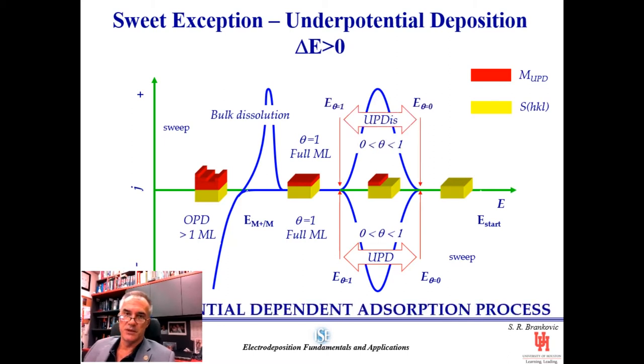The message to take home is that the UPD phenomenon is potential-dependent adsorption, and it's quite important to appreciate that by deciding which potential we hold the electrode at, we can actually control the deposition of copper to a fraction of a monolayer precision. This type of phenomenon and precision of deposition is only available in electrochemical systems, and UPD is a really unique phenomenon which we will further exploit in certain applications.